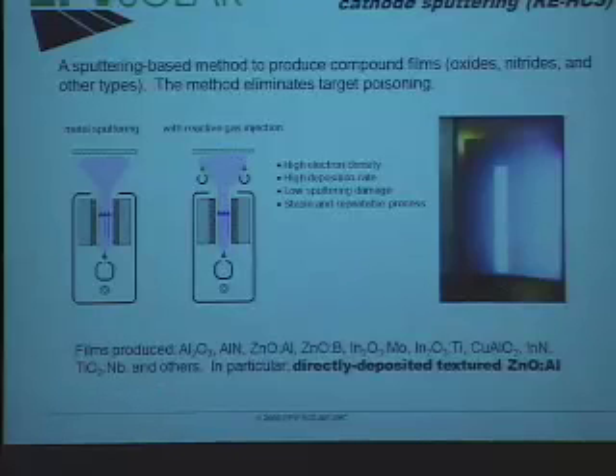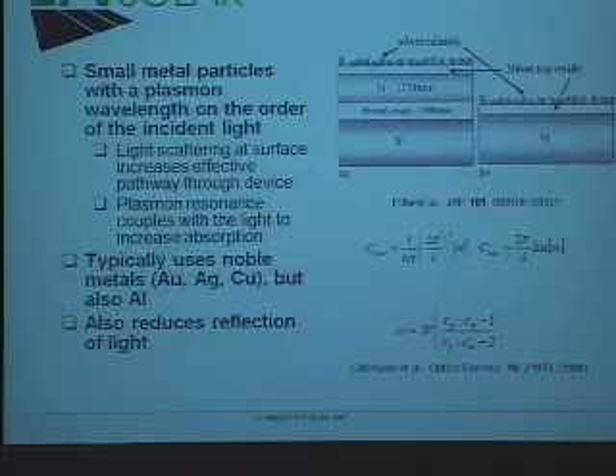We've made these different materials. This is what the textured tin oxide looks like. You can see plain glass here, looking through this piece of glass onto the table. It's beginning to look milky here with tin oxide. And with our textured zinc oxide, you can see it's a very hazy appearance. We're not just doing square centimeters, we're doing square feet here. Some other areas that may be applicable: microcontact printing could be applicable to developing these textures for TCOs, and plasmonics we would like to apply to increase light coupling or absorption in the active layers.